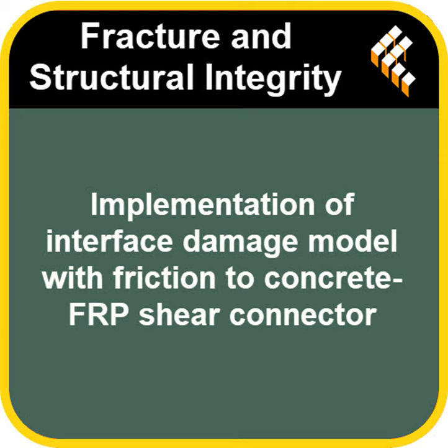So it's not just calculating if it breaks, but simulating the whole energy management process, even post-crack. Can you break down those energy ingredients again, simply? Sure. Think of it like an energy budget for the connector system. First, you have stored energy. That's the energy held in the materials as they stretch or compress, plus energy tied up in the interface's own deformation and damage. Second, energy from external forces. That includes the vertical pressure simulating the weight of the road deck above and the horizontal push or pull trying to slide the parts. And third, crucially for this study, dissipated energy. This is energy lost during damage, like when a crack forms and grows, and very importantly, energy lost due to friction as surfaces rub. They use a standard Coulomb friction model, which is a well-established way to calculate that resistance to sliding. So a really complete picture of energy flow during failure.